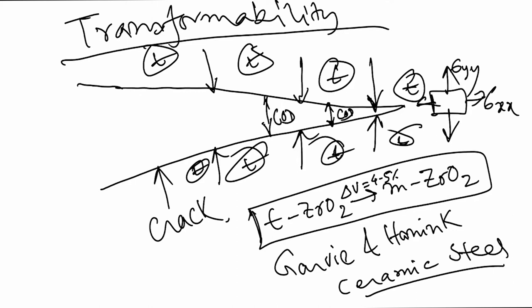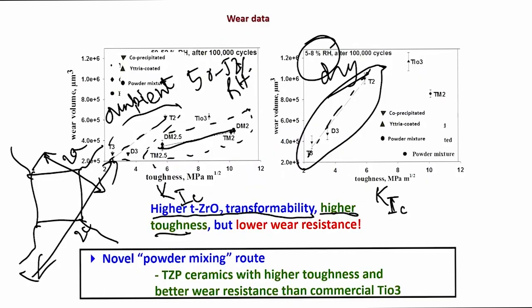The transformability is somewhat similar to hardenability, which is used for steels. So, if a steel is a very good hardenable steel, it means that the steel can be hardened very fast by simple heat treatment conditions without resorting to very aggressive heat treatment conditions. So, higher tetragonal zirconia transformability, higher toughness, but lower wear resistance. That is very important, because this lower wear resistance is a concern, and that can particularly limit the applications of these zirconia ceramics for various engineering applications.